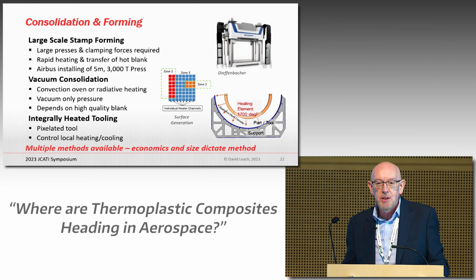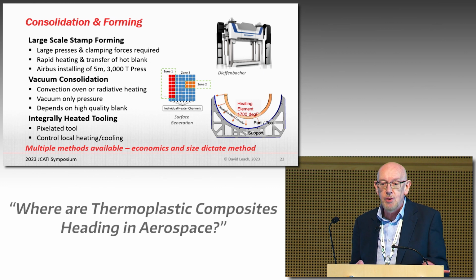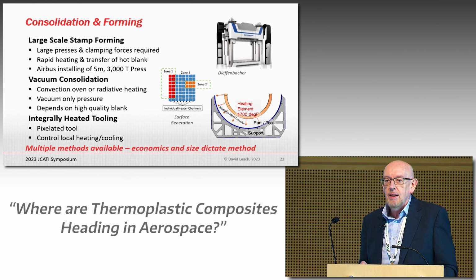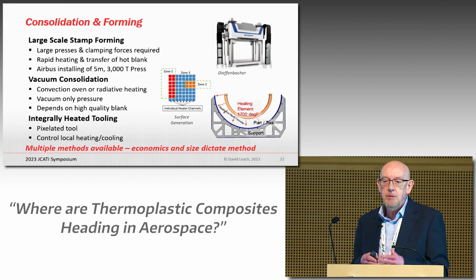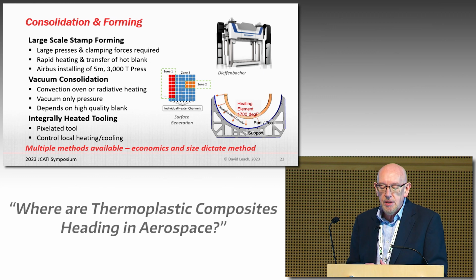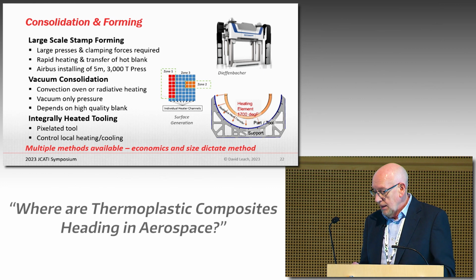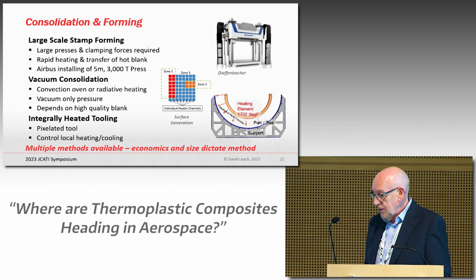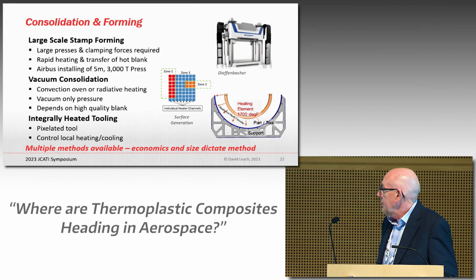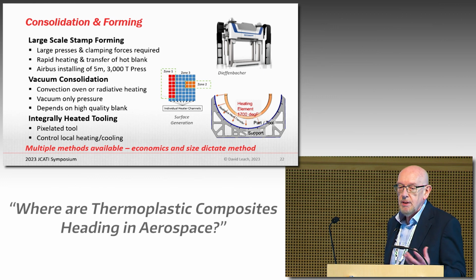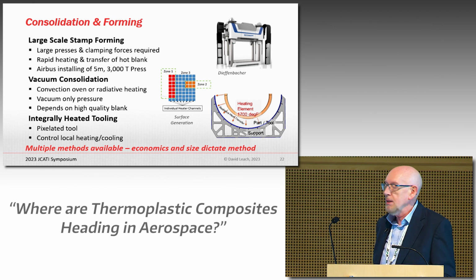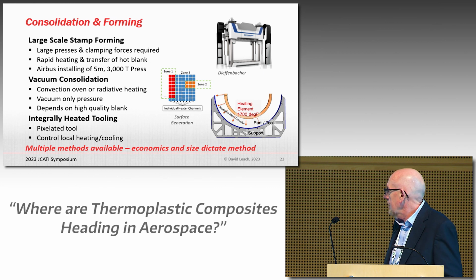The other extreme in terms of pressures, if you like, is just to go to vacuum consolidation. Again, if you get a highly compacted blank, typically with an AFP process, then you can probably get that to full consolidation. And there's been a number of demonstrations of that, either purely in an oven, again with a reusable bag, or as an example, you can actually use autoclaves, but rather than using the normal heating of the autoclave, you'd actually put in a heat blanket, which will just heat the local area in order to get the material melted and again flow.